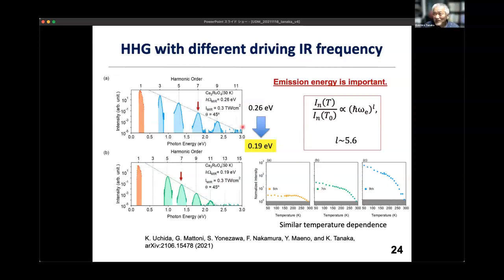And we found, very interestingly, if you see the 7th harmonic, of course the excitation laser frequency is different, so the emission energy is different. But if you consider this emission energy, we can scale these enhancements everywhere. If you consider the 7th harmonic and take a ratio between the intensities at 2 temperatures, this ratio is described by the emission energy and also a power L. L is, in this case, 5.6. So everywhere we can obtain this kind of power dependence.